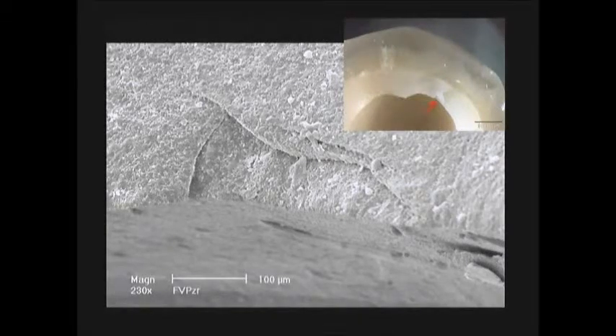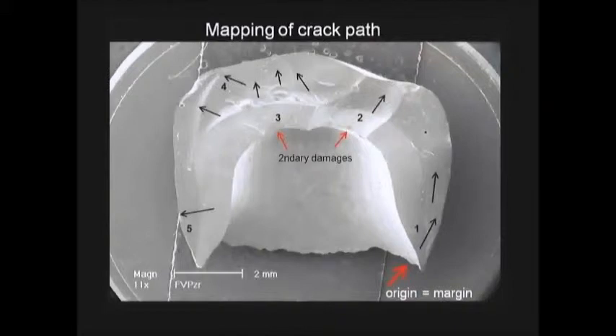Inside of the alumina crown that is positioned over a zirconia abutment, at that time just with a little fit checker in between, no cement. You keep mapping, so this and this are secondary damage because in essence the prime event is here, but then this one comes in as a secondary event because it breaks off a portion here.